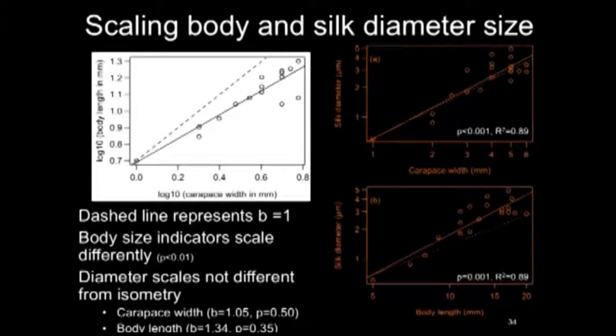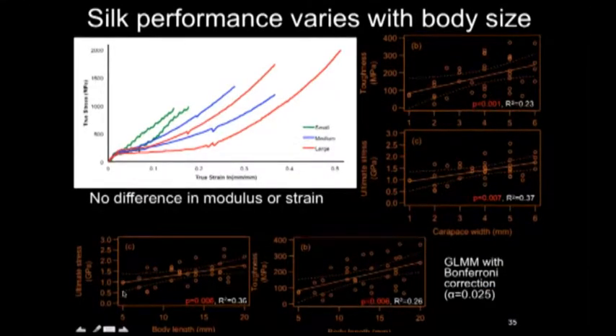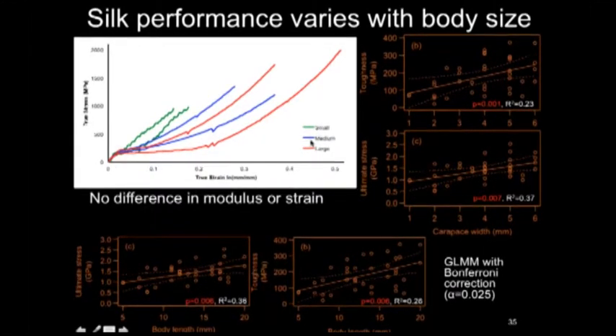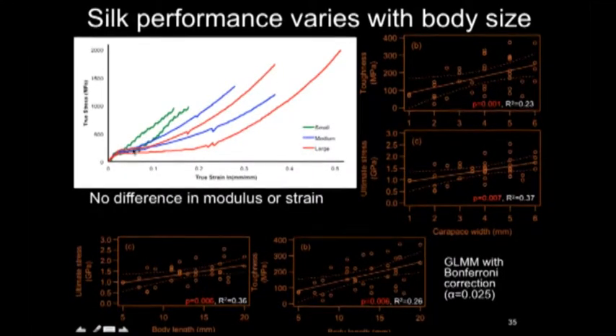And when we compare across spider size, then we do see changes in these mechanical properties. So from a qualitative perspective, by just looking at exemplar data, we see that the small individuals produce silk that is, you can see, clearly different from those of larger and larger spiders. Not only do we see that the breaking stress increases, and that's exemplified statistically across body size, both in our measure of body length and in carapace width, but also the area underneath this curve, which is toughness, this work performed.